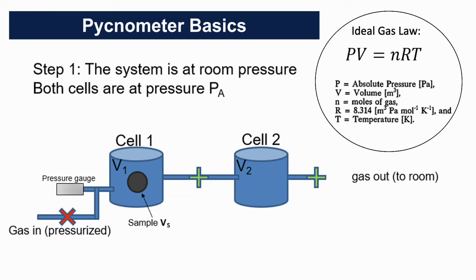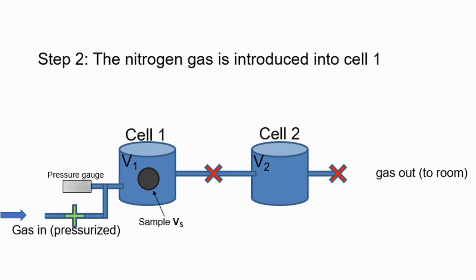The first step is to measure the atmospheric pressure using the pressure gauge, because the equations are relative to a vacuum, but this wouldn't be feasible for us, so we must measure the atmospheric pressure and subtract it from our other measured pressure values. The second step is to close the tubing between the cells as well as the exhaust tubing and introduce nitrogen gas into cell 1 to pressurize it.